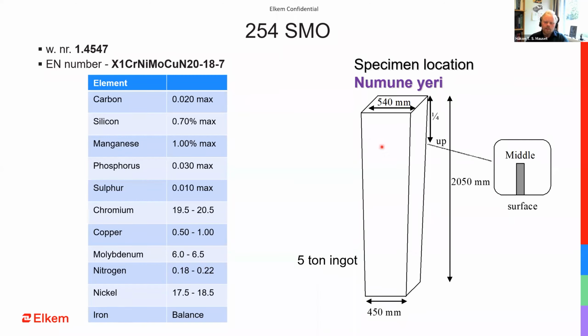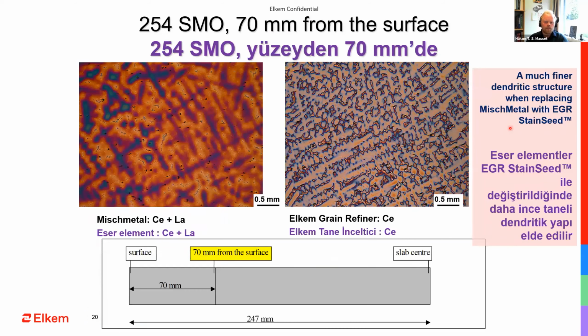So, but for this specific trial, a 5-ton ingot was cast. You can see it's about 2 meters high and 540 millimeters here on top. So what they did was that 1/4 from the top, they cut out a slice, and then they took out this test sample here from that slice. So here you have the surface, and here you have the middle. So 70 millimeters from the surface of the ingot.